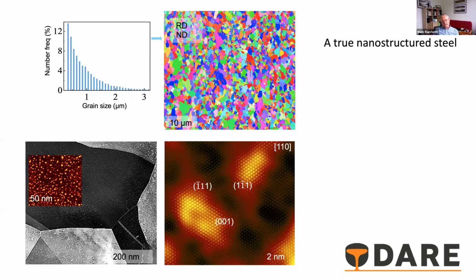Now, during that flash anneal, what we do is to precipitate a very high number density again of copper precipitates. So the bottom left there shows the distribution of the very fine copper precipitates, showing up as bright blobs there. And in the middle bottom, that's an atomic image showing the interface between the iron matrix, which is FCC in this case, which still does have some copper in it, but it's predominantly iron manganese. And then these regions that are precipitates, which are copper rich, but they also have iron in them. We have perfect coherency between them. And as you can see, they really are very fine, in the sort of 2-3 nanometer range.